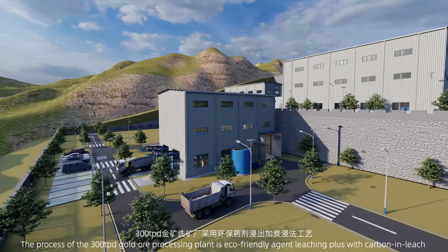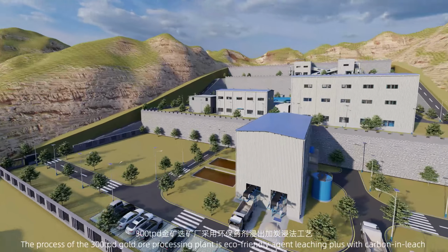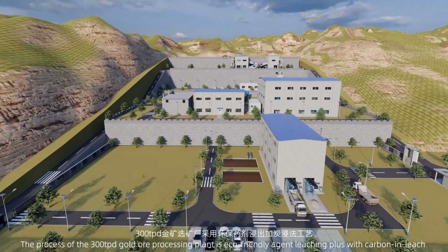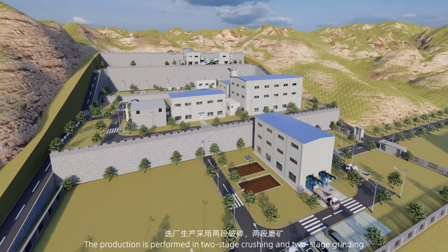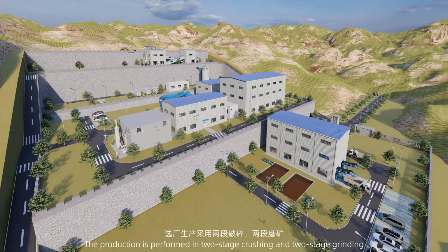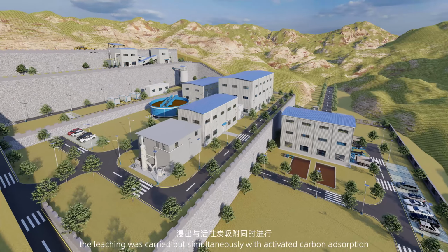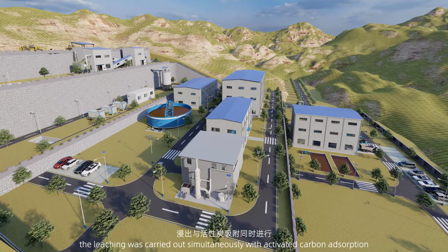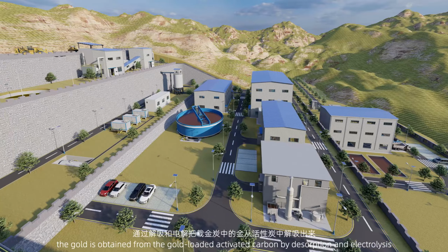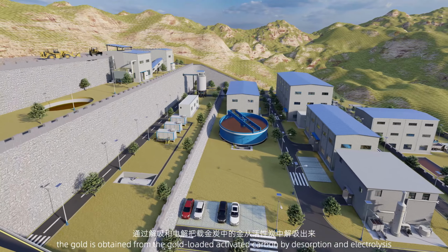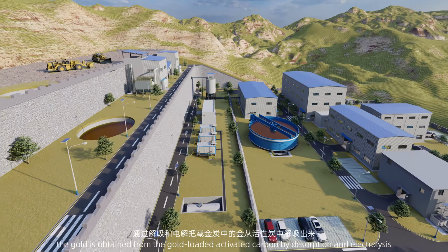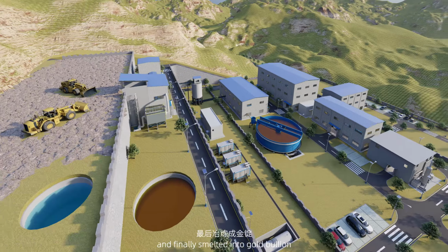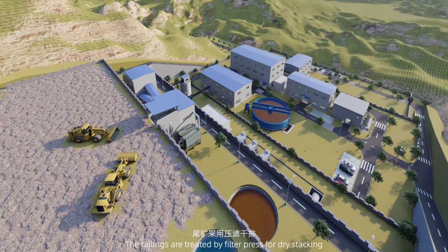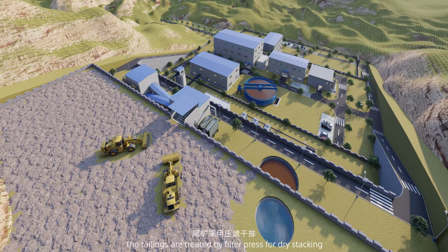The process of the 300 TPD gold ore processing plant is eco-friendly agent leaching plus carbon in leach. The production is performed in two-stage crushing and two-stage grinding. The leaching was carried out simultaneously with activated carbon adsorption. The gold is obtained from the gold-loaded activated carbon by desorption and electrolysis, and finally smelted into gold bullion. The tailings are treated by filter press for dry stacking.